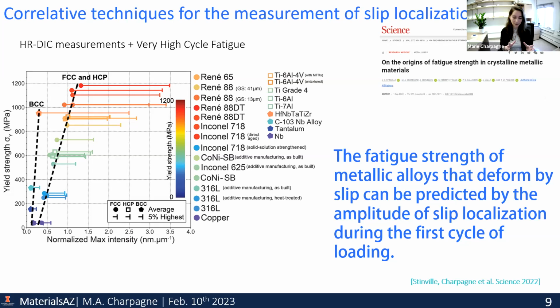So that proves what I was showing initially in the first slides, where I was showing in the first cycle formation of different slip bands. Now that we can measure their intensity over statistically representative areas, we can actually connect this to macroscopic properties such as fatigue strengths, which is what we did here, and find out some universal correlations. So this was published just last year, and I think this is the major finding with this technique.